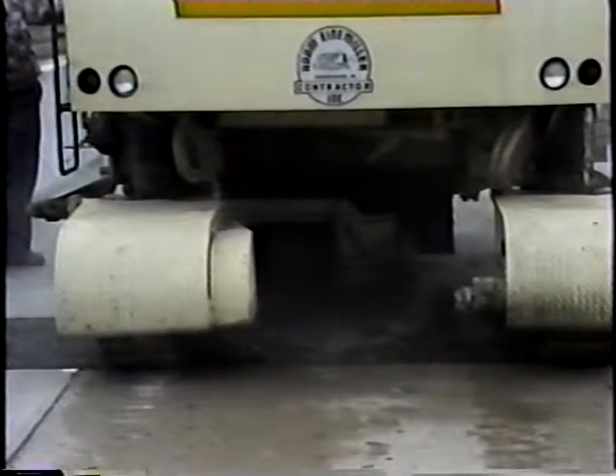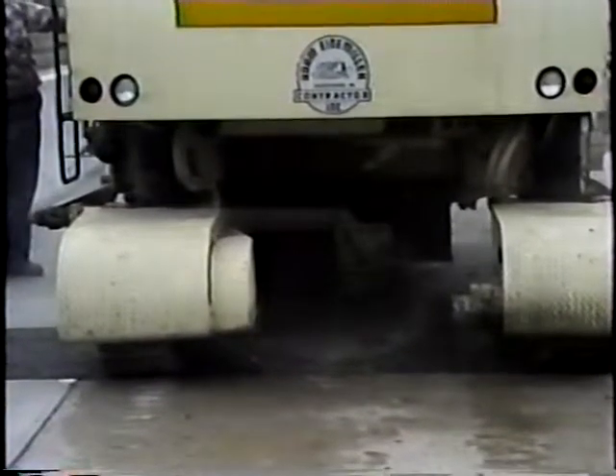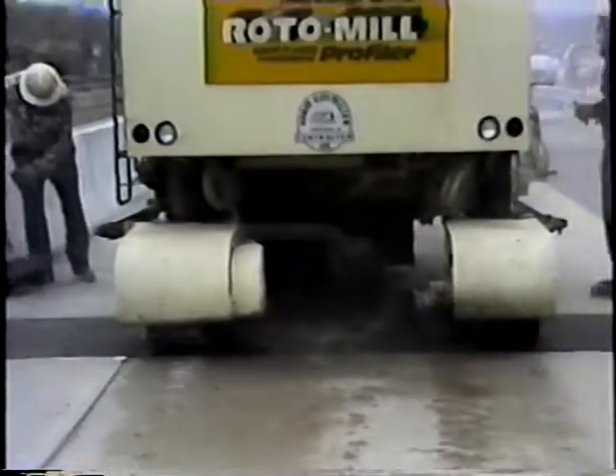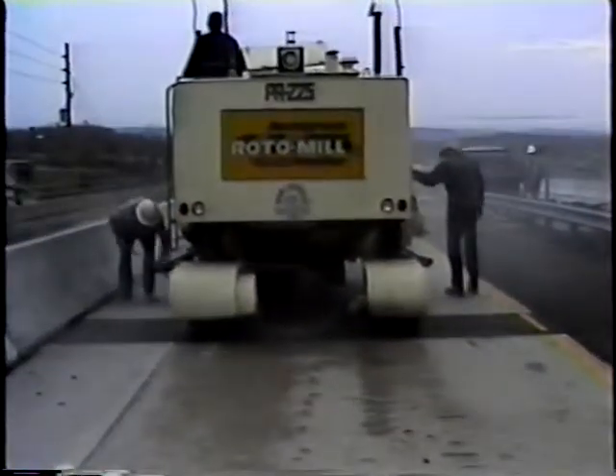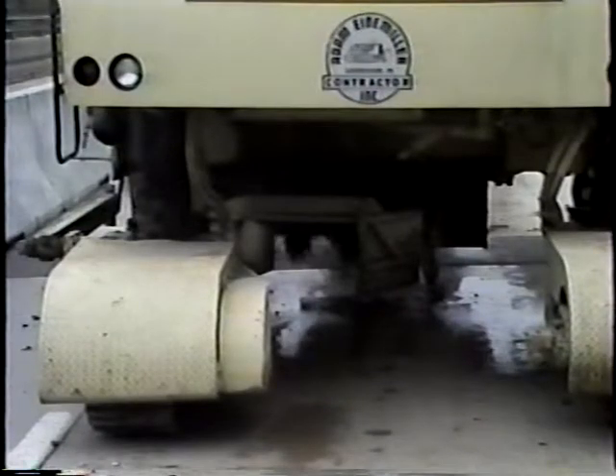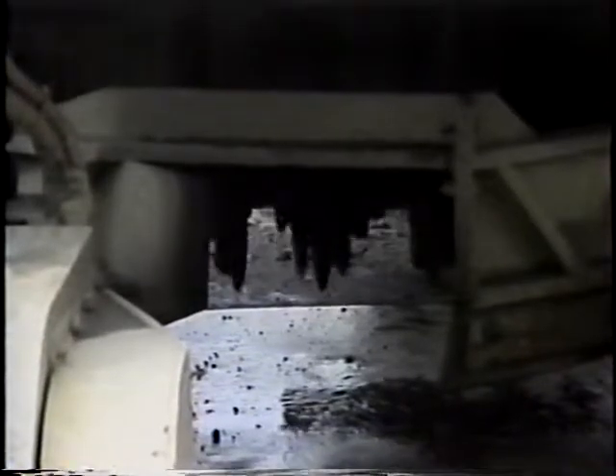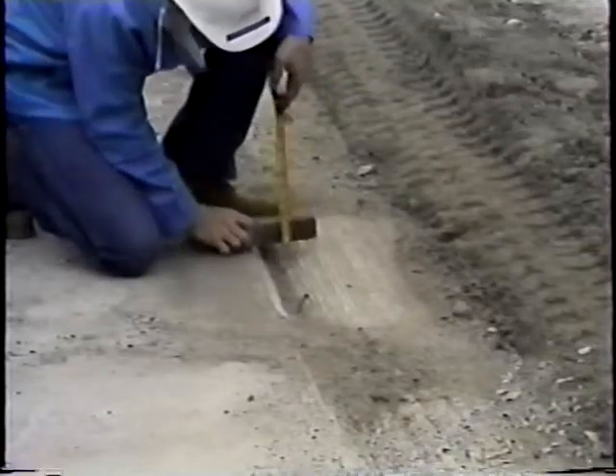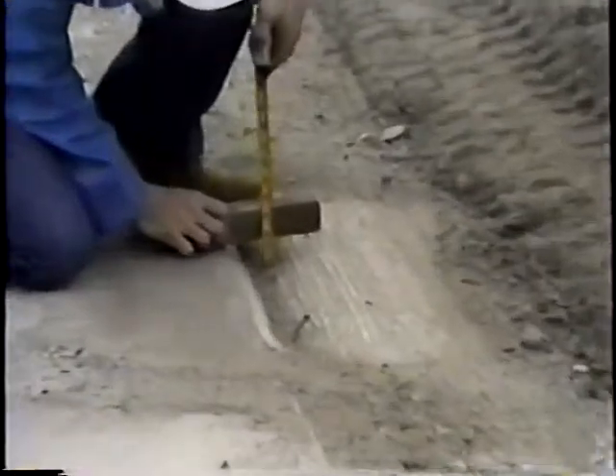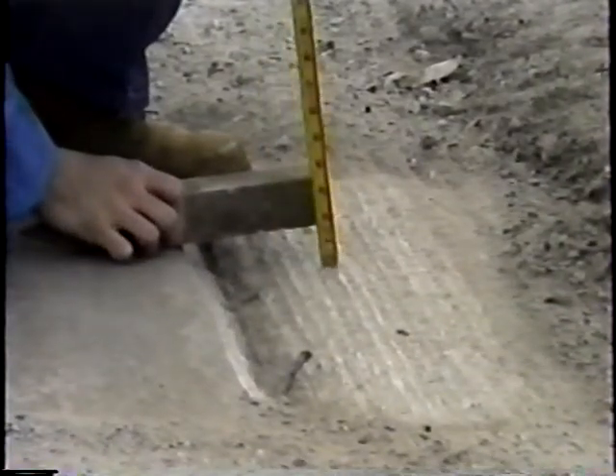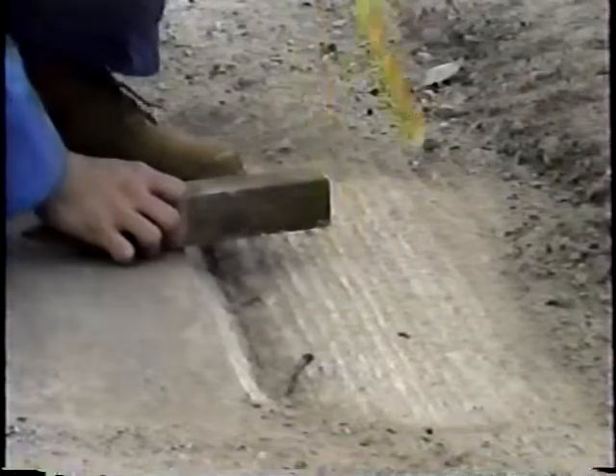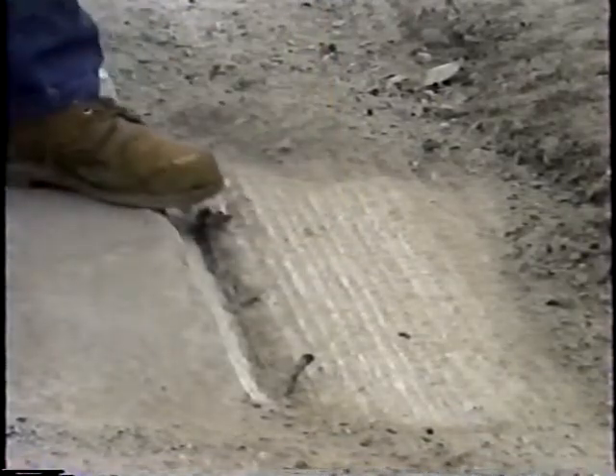Cold milling is especially effective for repairs extending across a major portion of a pavement, such as in full lane width repairs. Carbide-tipped milling machines and diamond blade grinding machines work particularly well because they can be preset to remove material to a specified depth. Although these machines produce non-vertical faces on two sides of the repair, they usually don't cause edge spalling, commonly associated with feather edging.